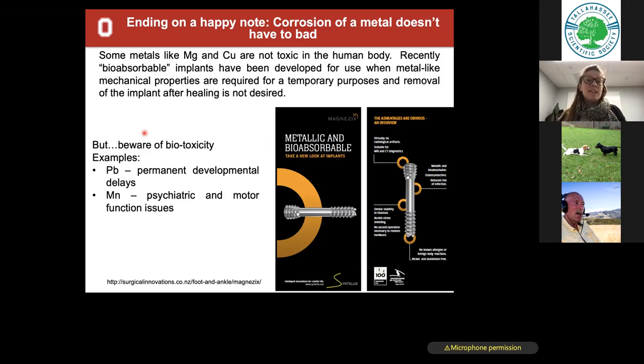But beware, right? There are toxicity issues. You have to be mindful. You can't just go put any old screw in your body and hope it will corrode, right? As we talked about, lead causes permanent developmental delays and cognitive delays. Manganese, if it's in really high doses, can cause motor function issues. So you can put a little bit of manganese in your body and it will corrode, but you don't want too much. So when you think about materials you want to put in to corrode and be bioabsorbable, you have to be real careful what you put in. But there's a lot of research done to understand corrosion properties. How do you tailor them? And what kind of tolerance do you have of different metal ions in your body in order to be able to utilize this? There are also people who do research in allergies and how corrosion of these materials might affect allergies in people.